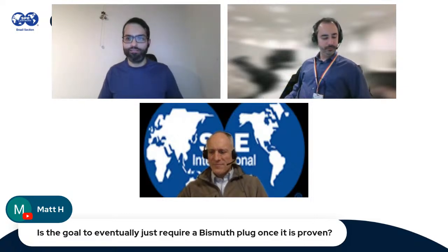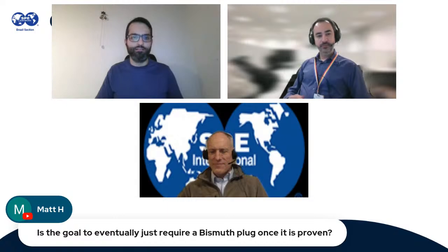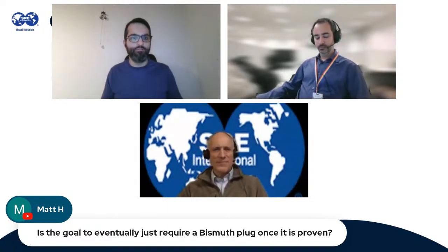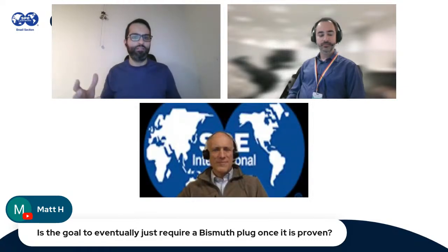So from the test phase, I think it was the first question. During testing, if you want to test the bismuth plug nowadays, you have to do this with cement, because according to the current standards, we cannot just deploy bismuth as the sealing material without having anything that is approved as a sealing material, since bismuth is not approved.